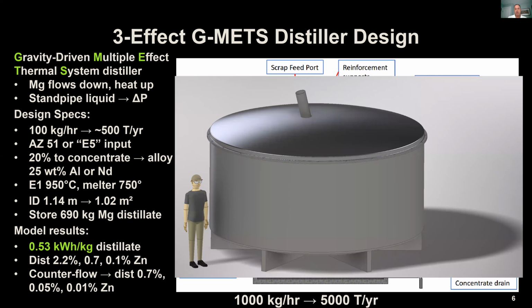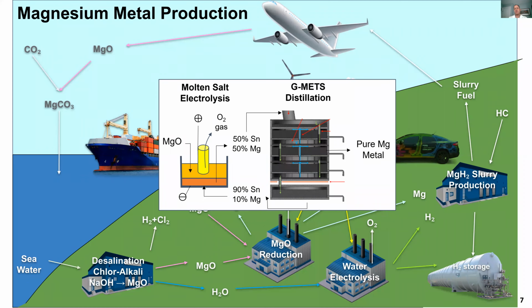Even better, we can scale it just by making it wider to increase the surface area and production rate. And that larger distiller loses even less energy through the sides per unit production. Back to the reduction process, our first trials with molten salt electrolysis have achieved 97% current efficiency, that is Faraday conversion of current to magnesium metal. And our 1 and 2 effect batch distillation experiments to date have validated the heat transfer models, not just validated them, but nailed the predicted heat balance within 1 to 2%. This gives us confidence in our designs from the first continuous distillation experiments planned for this fall to our pilot and full-scale design studies.